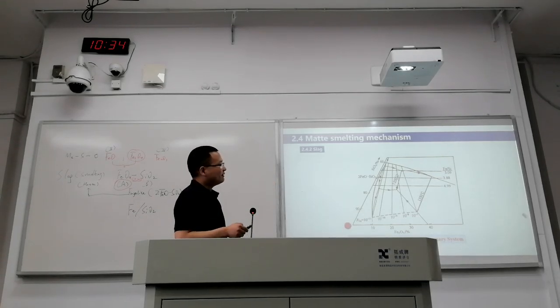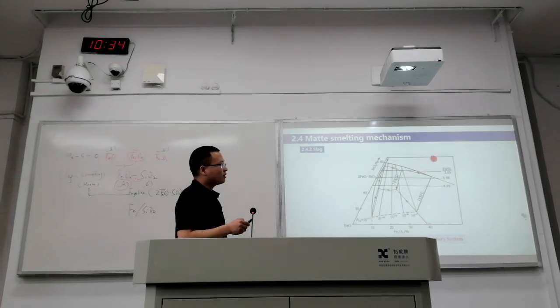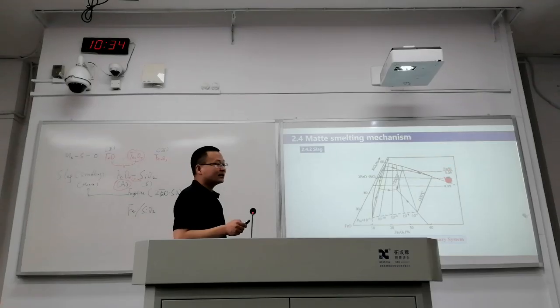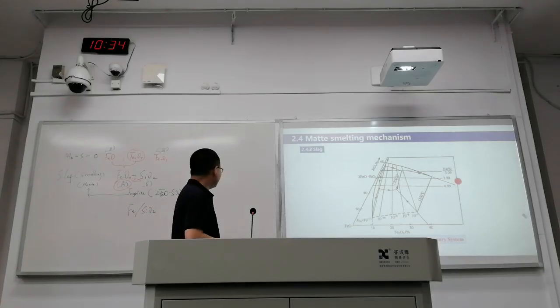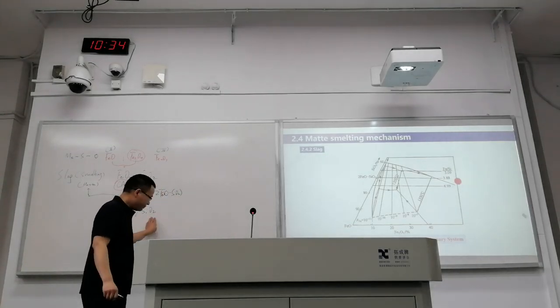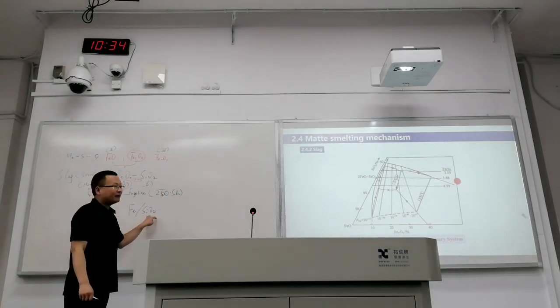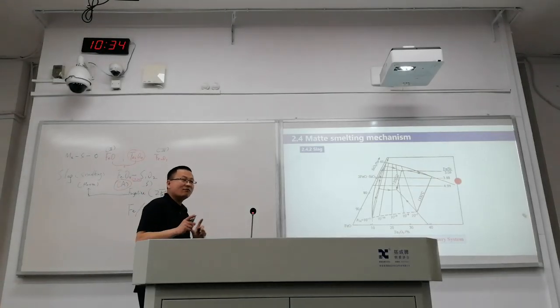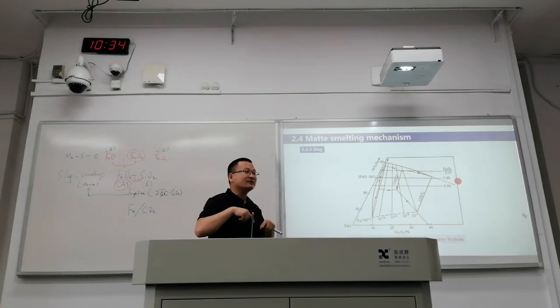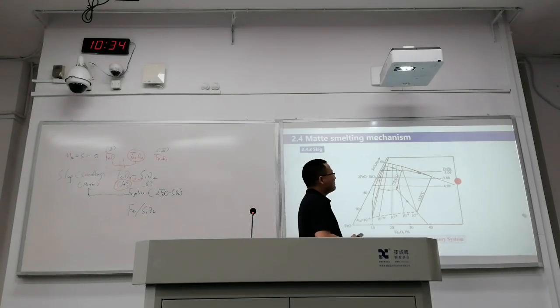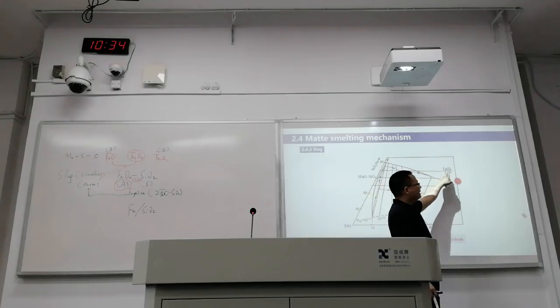But I don't like this one. So Fe plus silica. This is not a proper form for the iron to silicon ratio. This is not the proper one. If we are referring to the iron to silicon ratio, it should be silicon oxide. But this is the original phase diagram. We picked it up from a reference. So this number should be divided by 2, SiO2.